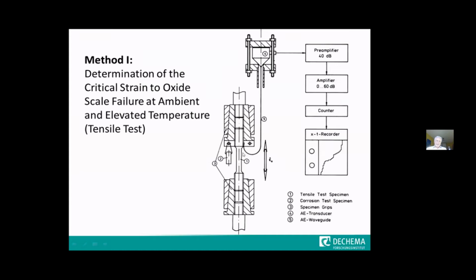So acoustic emission is always a good tool if you have brittle materials, because then you get quite strong signals in this case. Such a combination allows to measure the failure of the brittle surface oxide, and you can distinguish this quite well from the ground noise. I would call it the ground noise of ductile deformation of the metal.